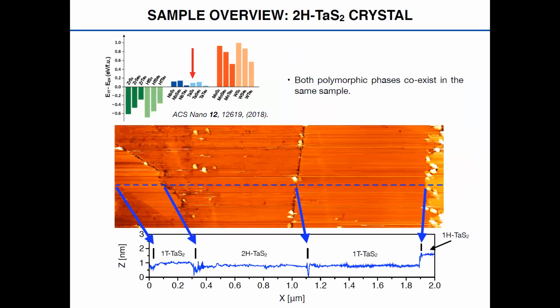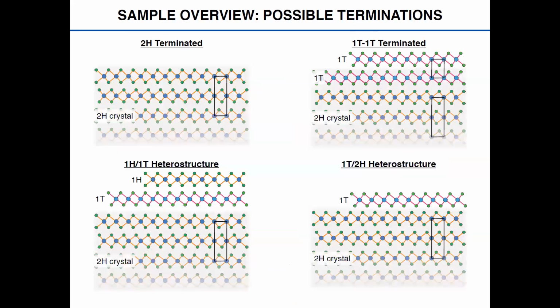When the surface of the sample after cleave is relatively clean, this is an image of more or less 2 micrometers. And much to our surprise, at the start, what we saw is that both polymorphic phases of tantalum disulfide coexist in this sample. So you have in the surface of the sample both the H and the T phase. And we explain this because the difference in the formation energy between the two polymorphic phases is very small. And therefore, when you cleave or when the sample is grown, you can have these two polymorphic phases coexisting.